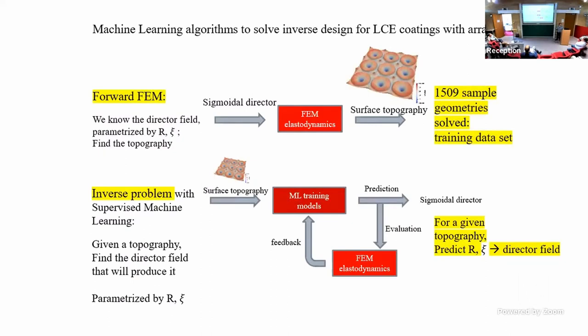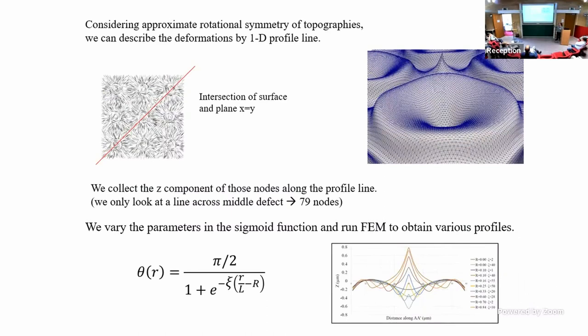Okay, so the forward problem, we ran it about 1500 times for different combinations of parameters. And then the inverse problem is going to be trained on all that forward data. And then we'll give it a shape and say, how do we make this shape of a suction cup or whatever thing? And it will tell us the two parameters that define the director field that give us that shape. Instead of doing the whole two-dimensional data set, we cut diagonal lines across it. Instead, in the topographic shape transform shape, there's a height as a function of position along that line. We'll use that data as our training data. And so you get different profiles for different values of the two parameters.